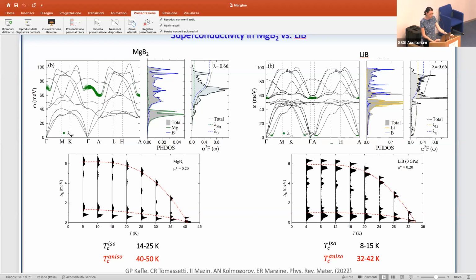In order to reduce the noise in our calculation due to mu star, we have compared two values, mu star 0.1 and mu star 0.2. Here I'm showing the results for mu star 0.2. What we found is that for the isotropic case, we get the same agreement that was initially predicted, that the Tc will fall between 8 and 15 Kelvin. But when we solve the anisotropic Migdal-Eliashberg equation, we get an estimate which falls between 32 and 42 Kelvin. So this is about three times larger than the isotropic prediction, and about 80% of the estimate for magnesium diboride.